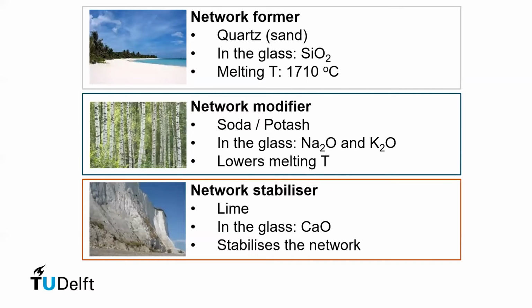Glass is generally considered to be a combination of three main ingredients, to which other elements can be added to create color, for example. But typically it's three ingredients: a network former, a network modifier, and a network stabilizer. The network former is the main backbone of the glass network, chemically speaking, and it consists of silicon dioxide, and the raw material used is quartz, so sand.